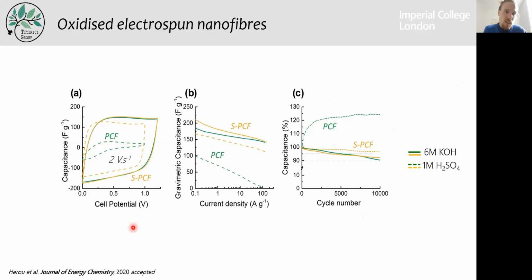Here we measure the supercapacitive performance in 2 different electrolytes, in 6 molar KOH and in 1 molar sulfuric acid. And we see that in KOH, the performance of these 2 samples is very similar. That leads to a capacitance of 200 farad per gram and a fairly good capacitance retention at high current density. And here in sulfuric acid, we observe a massive difference in performance, where the stabilized sample maintains really high capacitance, but the non-stabilized sample has fairly low capacitance.